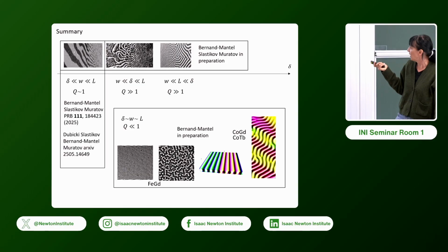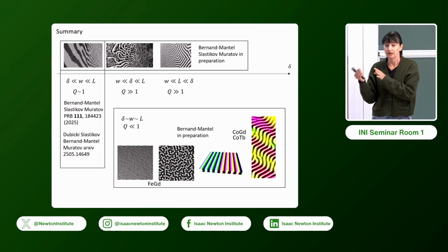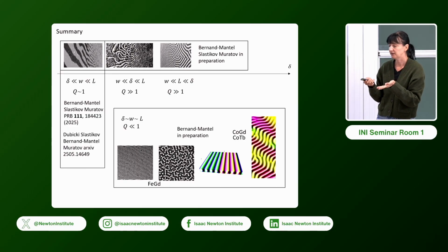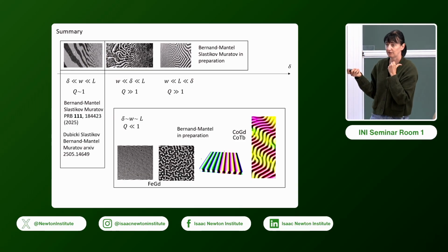Actually, why is this system interesting? It's because in the middle of the layer, you have this Bloch rotation. And what I didn't say is that the Néel rotation induced by DMI is homochiral. But the Bloch rotation favored by the stray field is degenerate. It can be in one direction or another. And this makes the system very interesting because your stripes, in their core, they can be like this or like that. So this is what you see here in this simulation.